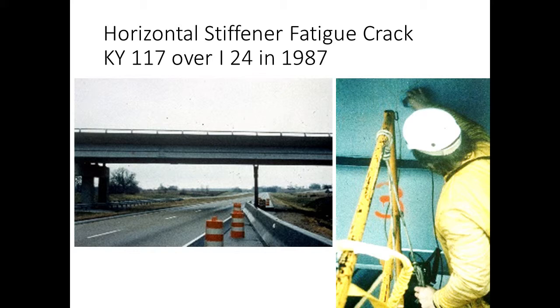If we look closer, what we see is that the web of the fascia girder has about been completely severed by a crack. The crack also goes through the horizontal stiffener, and you can see an inspector using ultrasound, trying to find the crack tip so he can cap it with a check hole. Eventually this crack was repaired by lapping with bolted splice plates.